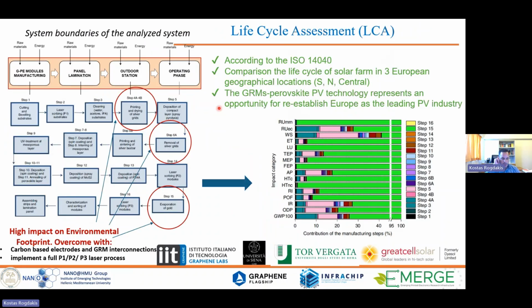At the same time, we also performed some LCA analysis, life cycle assessment of the technology, and we identified that the bottlenecks are the gold evaporation that is still present on the panels. We have to replace gold, probably with carbon-based material, in order to make a more sustainable technology. And also this drying and laser process here for the scribing of the panels is also a negative part in the LCA analysis.